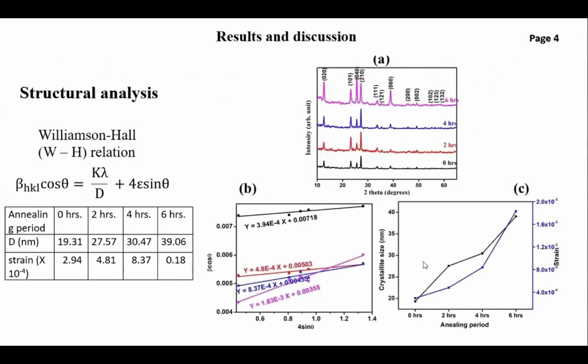Now, results and discussion. For the structural analysis, as we can see from figure A, the peaks related to orthorhombic molybdenum oxide films have been seen with 020, 040, 060 peaks and the rest. The existence of 0k0, where k equals 2, 4, 6, confirms the production of the laminar crystal structure of molybdenum oxide films. As we can see, the preferential growth is in the 0k0 direction. So this indicates that the preferential growth occurred in this crystal plane of 0k0.